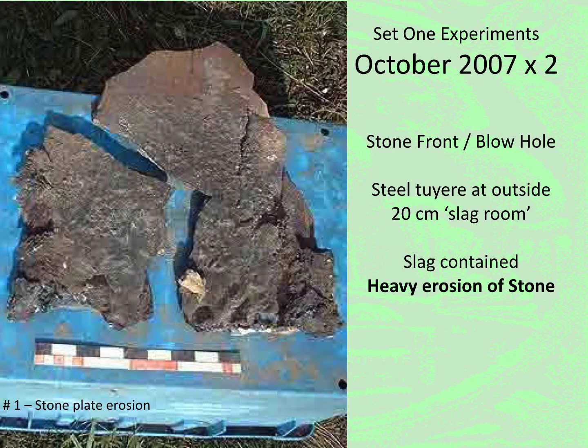There was quite heavy erosion of the schist stone slabs used to construct the furnaces, starting at about 4 centimeters thick, but eroding down to 1 centimeter thick by the end of the smelt.